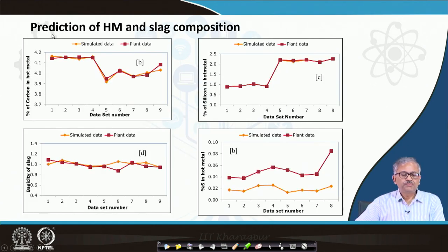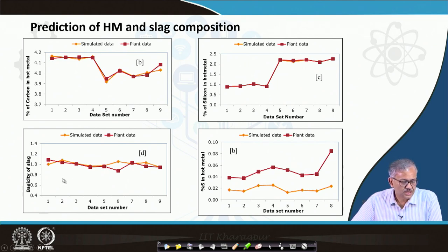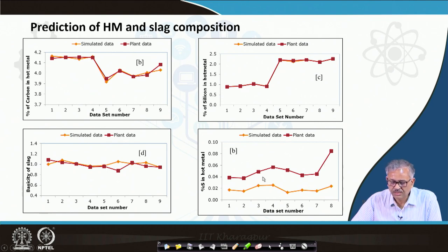Now if you want to predict the hot metal and slag composition, you can see there is a close match with different data sets: percentage carbon in the hot metal shows a quite good match, percentage silicon also good match, and slag basicity for different data sets also matches. For sulphur there is a slight difference — sulphur prediction has been a little off — otherwise everything is okay. Basicity is of the order of 1.